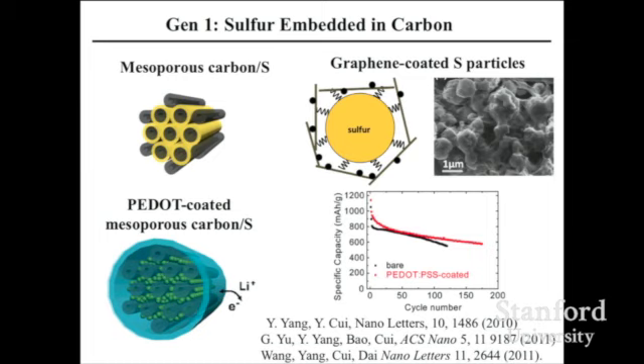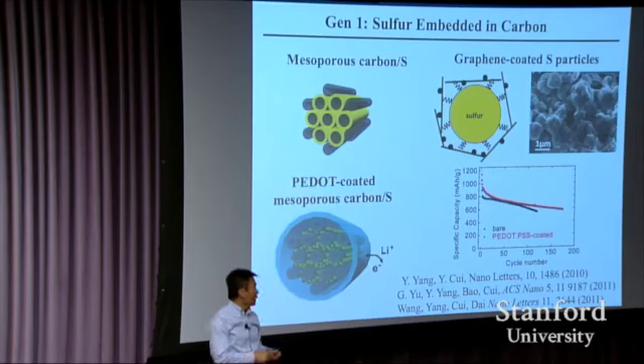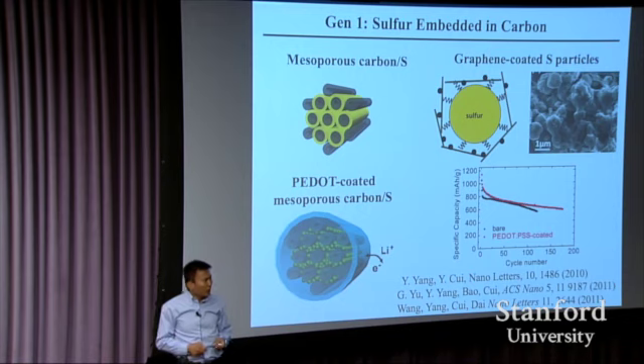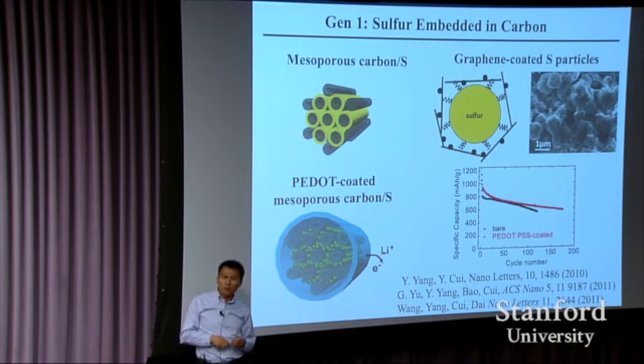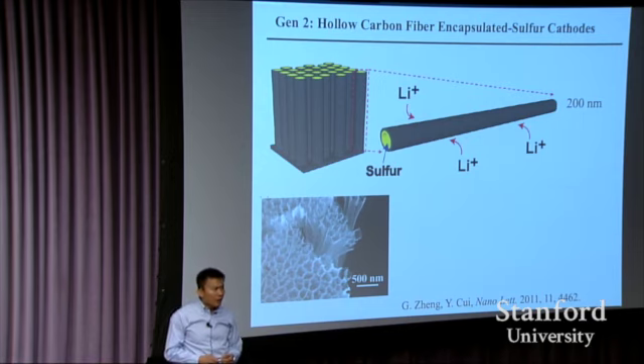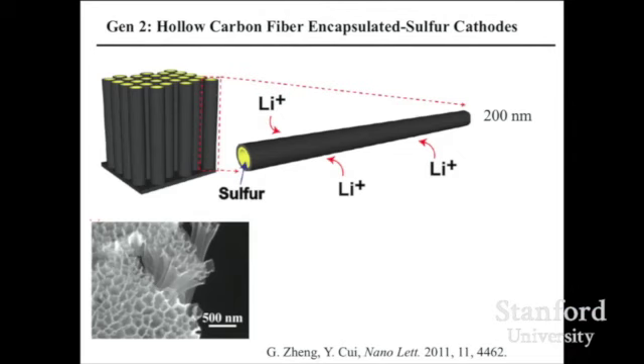So in the past several years, together with Zhenan Bao and Hongjie Dai, we came out with several generations of design, starting to embed sulfur into a mesoporous carbon using graphene capping, using polymer capping. We actually improved the performance quite a bit, but you still see the capacity decay. It's puzzling for a while. For about 2 years, I just felt like it's not possible to solve this problem, until we came up with new ideas. Research always goes like this, particularly for students, you've got to understand this. There's a very exciting period, and then a plateau sitting right there for half a year, a year, and nothing happens. If you just hold on very tight, something great will happen again. So this is exactly the moment.